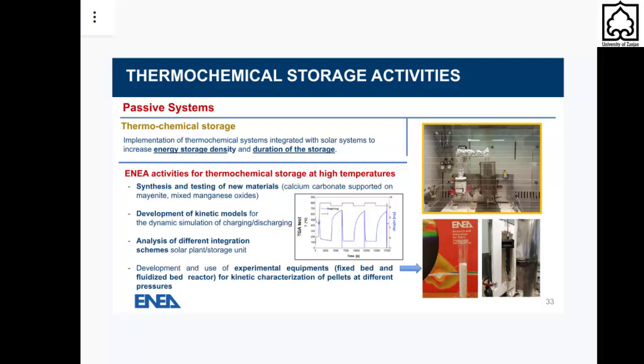To conclude this survey, I would like to briefly mention our work on thermochemical storage. Thermochemical storage is particularly promising because, in addition to a high storage density, which is theoretically up to 10 times higher than sensible heat, the thermochemical storage is virtually suitable for thermal storage on a seasonal scale, let's say allowing the storage of excess solar radiation when it is available.